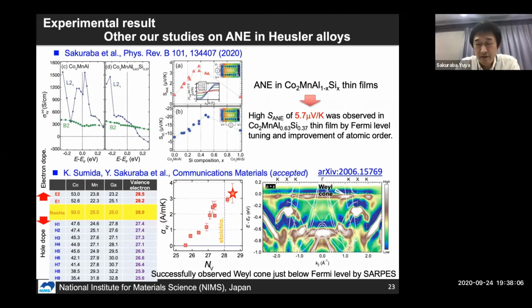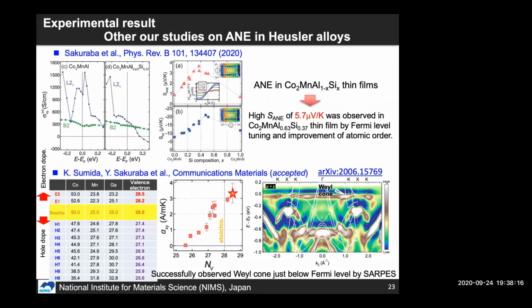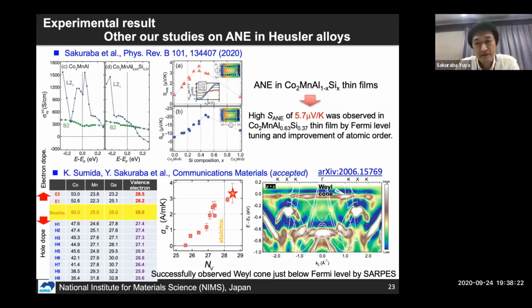Yes. So in this paper, we could not conclude that we observe the Fermi arc in this ARPES measurement. Okay, because if you have a gap, then it's not a Weyl point, right? While you should have a protected crossing. Yes. So here we should have the gap. Of course, because of the resolution, we could not see the clear gap, but there must be a gap.